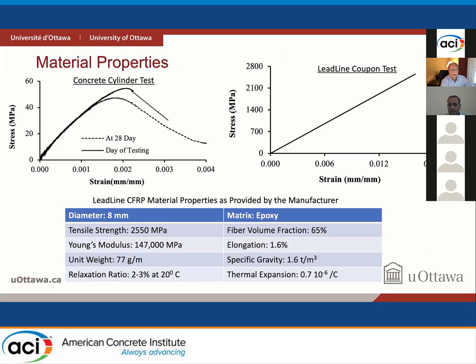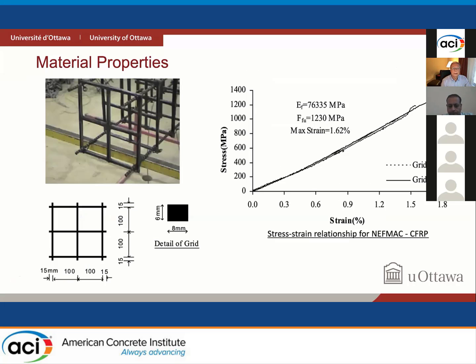Here you see stress-strain relationships for concrete. These are cylinder tests. So it's almost approaching high-strength concrete, and which is obviously compatible with high-strength reinforcement in this case. And then LeadLine coupon tests can be seen having over 2000 MPa capacity. And the table shows what was supplied by the manufacturer, which was verified by our coupon tests.